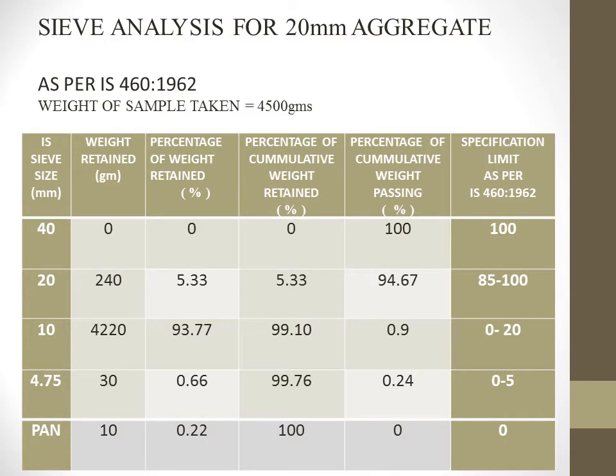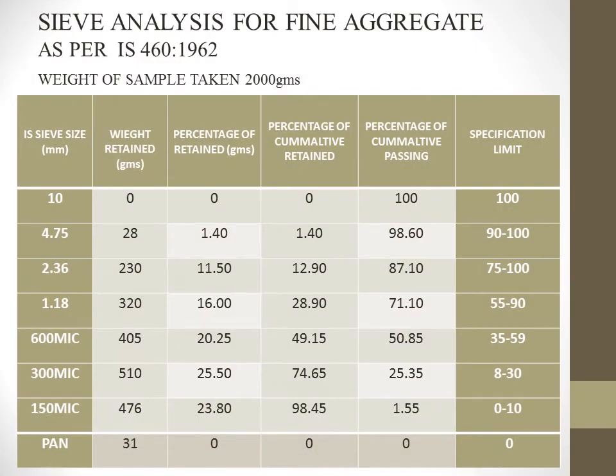This is the tabulation for sieve analysis on 20 mm aggregate as per IS 460 of the year 1962. We had put the 20 mm aggregate into various sieves of sizes ranging from 40 mm to 4.75 mm, and they had all complied with the specification limit as per IS 460 1962. And also we had done sieve analysis for fine aggregate with the sieves ranging from 10 mm up to 150 microns, and they had also complied with the specification limit of IS 460 year 1962.